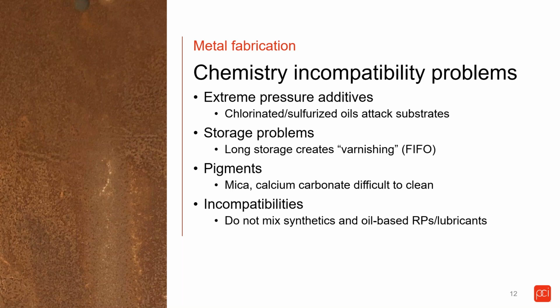Some of the pigments that were mentioned on the previous slide, like mica and calcium carbonate, can also be a little difficult to clean. And lastly, and this is probably one of the most important ones, don't mix a synthetic lubricant with a straight lubricant. You might have a good synthetic lubricant and a good straight oil, and you might think, oh, well, let's put them together and make it great. Well, what you're going to end up with is something similar to a varnish, and you're going to pretty much have to dispose of all of those parts.